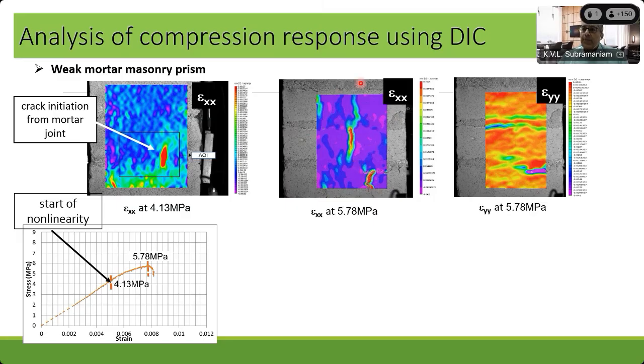And what you see is the failure is produced by the splitting cracks that run all the way through the height of the masonry. This is for the case of the weak masonry that we are looking at here, and irrespective of whether we're looking at weak or strong masonry, the stress state is such that the tension cracks are driven by the mortar. Mortar is locked in a state of very high in-plane tension. The mortar splits, cracks. The minute it cracks, it forces cracking in the brick, and that drives this vertical cracking in the masonry, and that is one of the modes of failure that we observe.